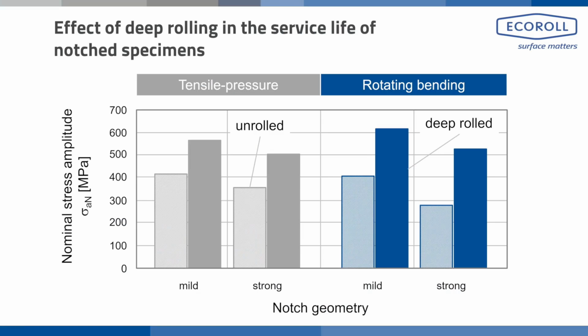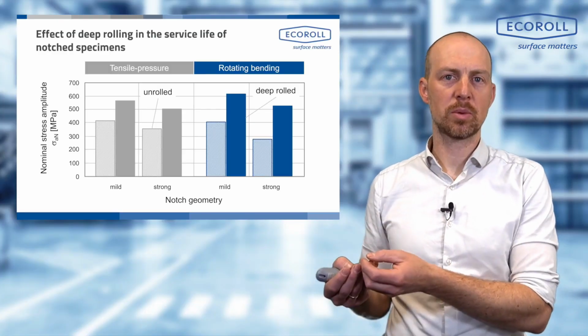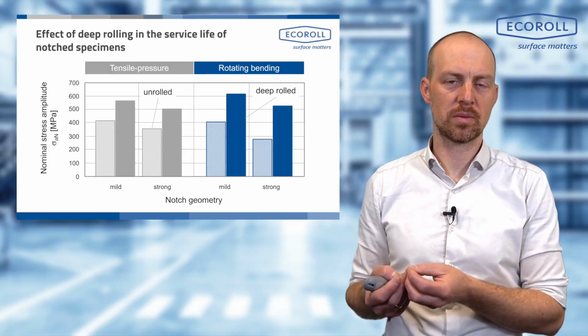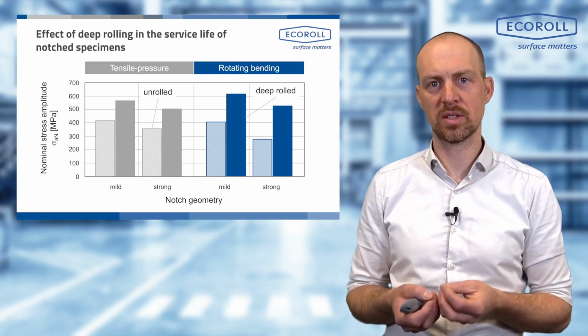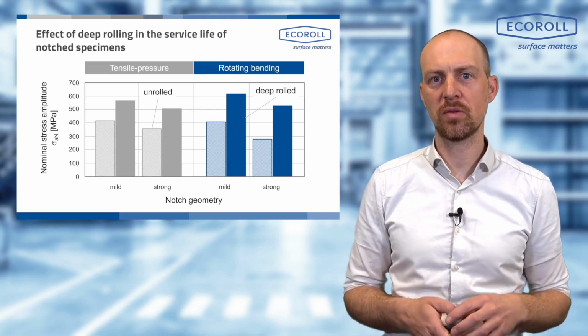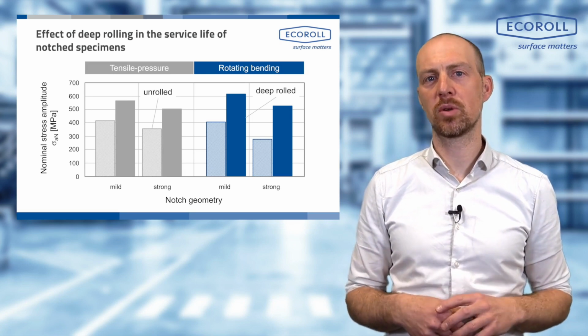Simply put in terms of values, we have almost a doubling of the nominal stress here. Do we still have a nominal stress with the unrolled sample of approximately 280 MPa, we are already over 500 MPa with the deep rolled sample. So nearly a doubling of this value indeed. This is an excellent result for the hard rolling and shows the great potential.